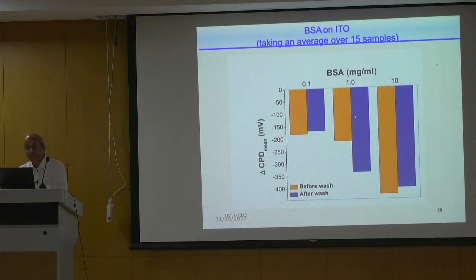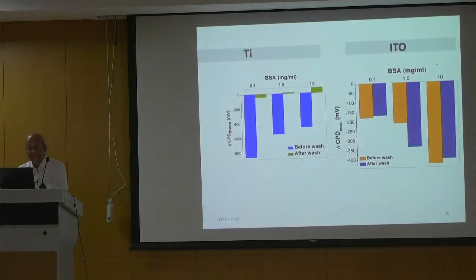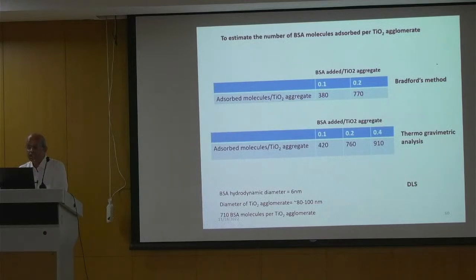Similarly, 1 milligram per milliliter, 10 milligrams per milliliter. And if you do it on titanium, the results are completely different. This is before wash, and after wash it has gone. It means that titanium does not behave exactly like ITO. This is a completely different surface. So these two are compared here, and we have also measured the surface energy.